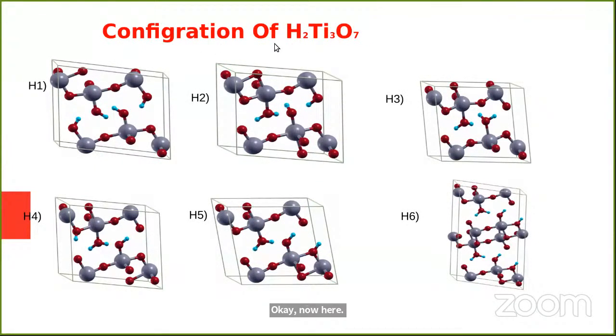Okay, now here we are going to look at the configuration of hydrogen titanate, because experimentally the position of hydrogen was not well determined due to the weak interactions in comparison to the other elements. And our calculation shows that half of the hydrogen forms water and the others remain in OH groups. In this figure, H5, this figure indicates the stable configuration with a single cell. And then we doubled this stable structure in the Y direction, and we got this structure. Our calculation confirms that the stable structure for hydrogen titanate has a double cell, and the single cell lies higher in energy by 0.14 electron volt.